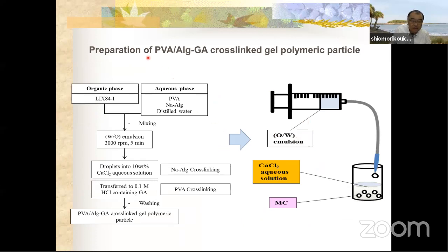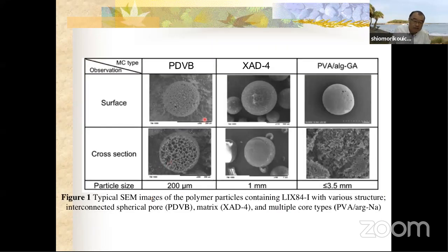This procedure is the preparation of a PVA alginate cross-linking gel containing extractant droplets to make a multi-core type microcapsule. After preparation of the W/O emulsion, the O phase is an extractant solution, and the W phase contains PVA and sodium alginate. After making the emulsion, it was dropped into the calcium chloride solution to make a gel microcapsule. After gelation, the capsule was cross-linked by GA.